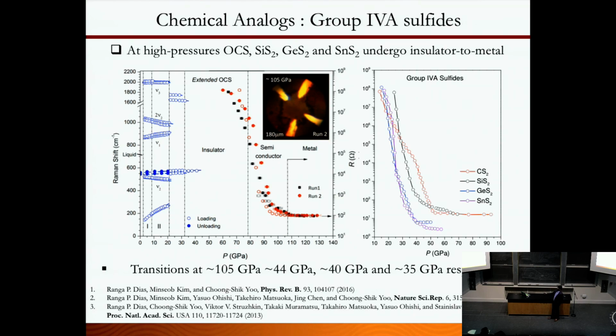So here you can see the pressure and the vibron frequency from the Raman shift, and this is the resistance, showing a 7 order of magnitude drop in resistance right here. And these are the frequencies, changing while you go through the pressure. You're clearly indicating a phase transition. And all the other materials, carbon disulfide, silicon disulfide, germanium disulfide, tin disulfide, all those materials have the same behavior and go to an insulator-metal transition, then superconducting, and these can be recoverable.